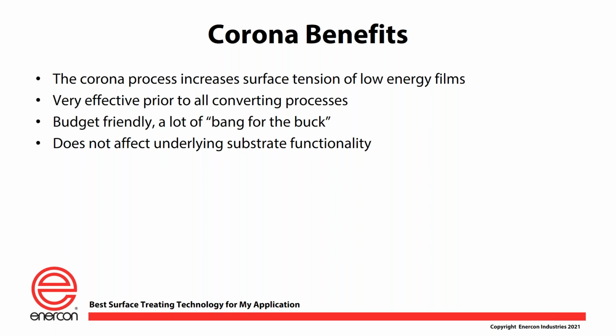Now there are different designs and different pieces and bits of corona treaters, but if you make it simple for yourself, all corona treaters ionize air. That's what corona is. And the process increases the surface energy of low energy films. So we take a polyethylene, let's say, and we run it through the corona treater, and we go from an inherent dyne level of, let's say, 36 dynes, and we can easily get that substrate up to 40 dynes, or maybe even 42 or 44 dynes.